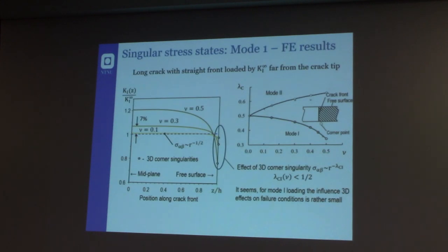So what we found out is that under pure mode 1, it's like what happens with the circular hole under pure mode 1. You have a stress field that is strongly changing along the thickness of the plate. So you have the maximum stress field in the mid plane of your component, and you have a decrease of the stress field when you are on the free surface.